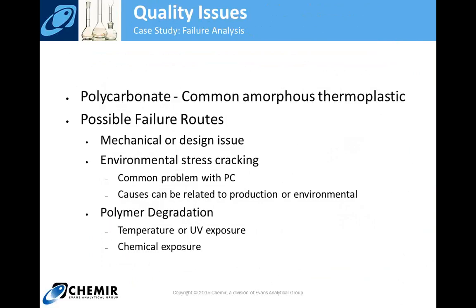Now, knowing that it's a polycarbonate immediately gets us thinking about possible failure routes. Polycarbonate is a very common thermoplastic resin, but there are known failure mechanisms of PCs, of polycarbonates. Part of a failure could be a mechanical or design issue, and that's really not what we're investigating at Chemir. We're looking for chemical reasons for a failure. But again, there could be a chemical or design issue associated with the failure. More often it's chemistry, degradation, like environmental stress cracking, environmental exposure to different chemicals that results in degradation of the polymer.